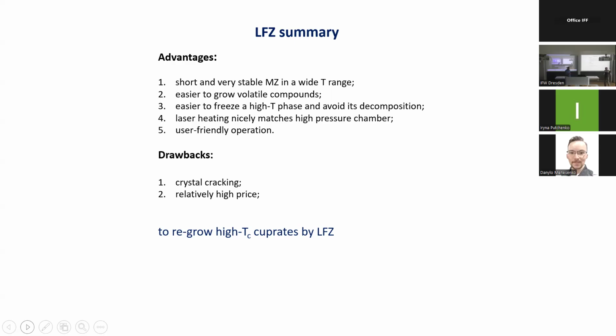Just go to the literature. We are not the first group having this laser floating zone. Did other people try to use this laser floating method to grow, for example, YBCO or Bisco? Among all high-Tc cuprates, there was one Japanese group that grew barium-doped La2CuO4, around this. Also Martin, Marcus did that. That's also possible now to grow this famous 1/8. Yes, exactly. Only this material was regrown by laser heat. Others, as I know, not.